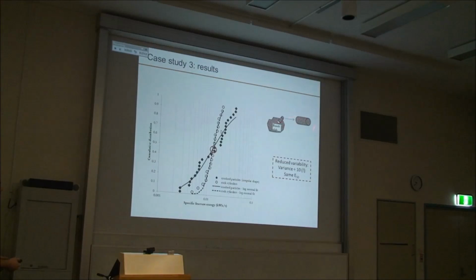So I went on and I did a test with a basalt sample. I drilled with a drill in a basalt sample, and here the black symbols are the crushed particles. So this is the roughly spherical, irregularly shaped particles.